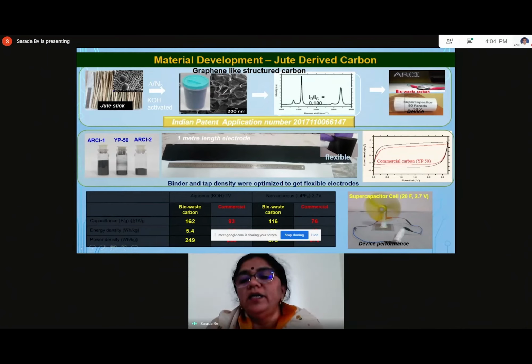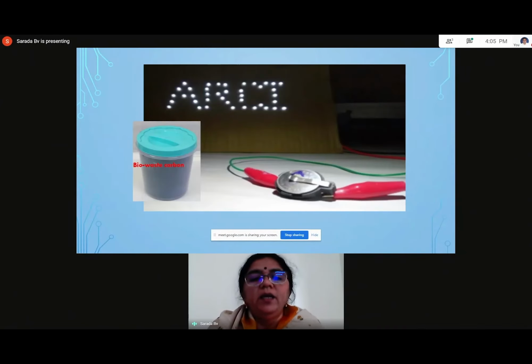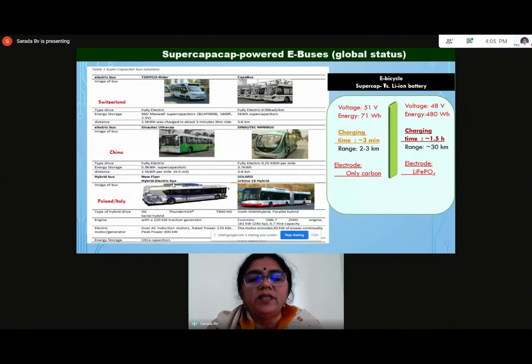And an EDLC capacitor is made by using this carbon substrate, and you can see over here that from the carbon made from the biowaste, the performance is much better even compared to the commercial ones available. And this is demonstrated at lab scale, and you can see that kilograms of this carbon could be made, and so that's how it is upscaled, which is in line with the mandate of ARCI.